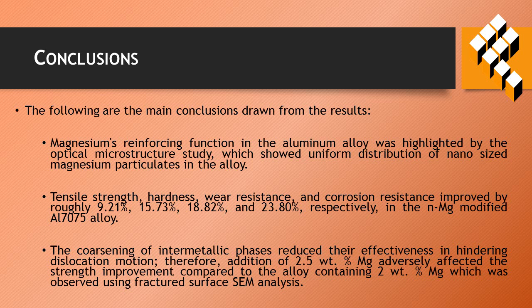The intermetallic phase reduced their effectiveness in hindering the dislocation motion. Therefore, addition of 2.5 wt.% Mg adversely affected the strength improvement compared to the alloy containing 2% of magnesium particulates, which was observed using fractured surface SEM analysis.